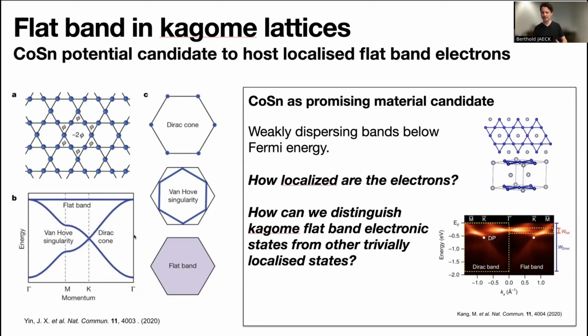First of all, you have interlayer couplings between the Kagome planes stacked in the out-of-plane direction. Now, obviously, destructive interference helps you to catch an electron and jail it in this honeycomb, but the out-of-plane hopping gives it an escape pathway, which is something you don't want. Also, just including spin-orbit coupling, which in most materials of interest is hard to avoid, the flatband gains a finite dispersion. So naturally, the question arises: which materials can we find with true 2D Kagome flat bands, and how can we make them useful, so to say?